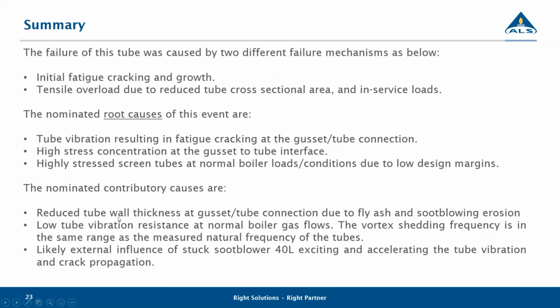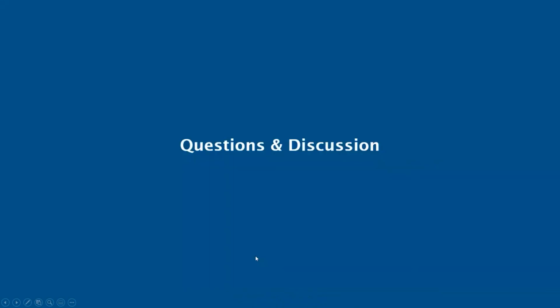Contributory causes are reduced tube wall thickness at that connection due to fly ash and soot blowing erosion, low tube vibration resistance because of the length of the tube. Vortex shedding frequency is in the same range, so you could get conditions where they match up. And also, what was interesting, two of the failures where we had that rapid sort of failure occurred with a stuck soot blower in the furnace. So we also suspect that that soot blower, stuck at that location, has an impact on the vortex shedding frequency and possibly excites that tube. So that's in summary. It's an interesting one. If there's any questions, please feel free to ask.